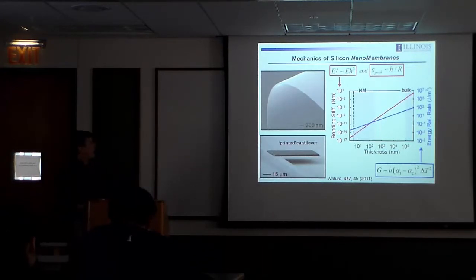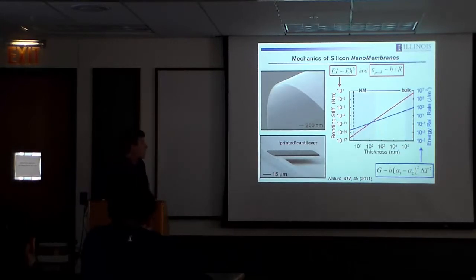And that renders a relatively large bending stiffness. So the bending stiffness scales like the product of the modulus of the material. That's sort of intrinsic. You're not going to change that. But it also depends on the cube of the thickness. So if you plot the bending stiffness as a function of thickness, you see that you have a value for silicon that's around 10 newton meters for a wafer scale thickness, so maybe a millimeter.